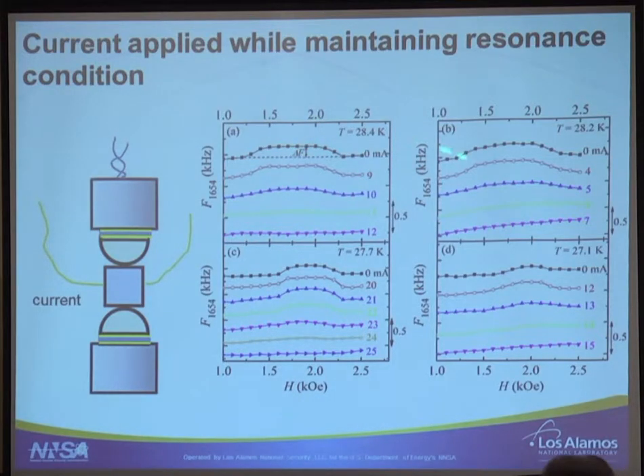In both cases, you see at all the temperatures, we see a jump. And depending on where we are in temperature, closer to the end of the phase diagram or in the middle, we see this jump bigger. And this is basically the stiffness of the lattice as a function of temperature. But now we apply current. And what we see is that basically it doesn't change, so it's 0 and it has a bunch of different currents. At 0 and 9, you basically don't see much difference.